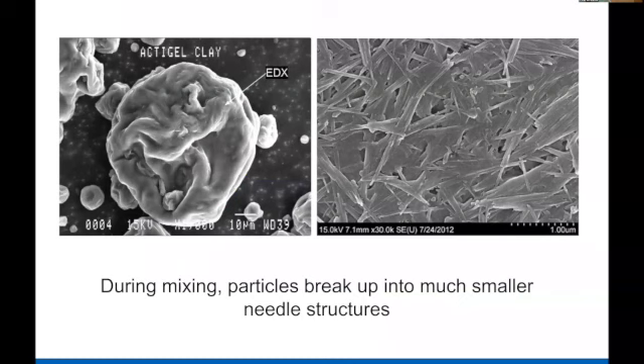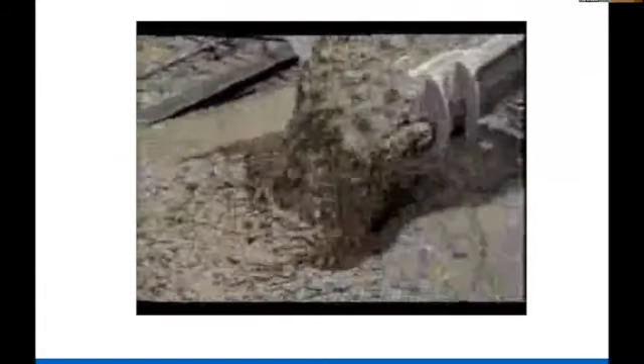Nanoclay, here for example, we are using attapulgite, which is a magnesium aluminosilicate, and we do it by calcining it and purifying, and then with ultrasonication so that it's separated into nanoplates. And I want to show one very interesting observation of nanoscale in rheology. And this is becoming important, for example, in 3D printing. So what I want to show you is one application of nanoclay in self-compacting concrete.